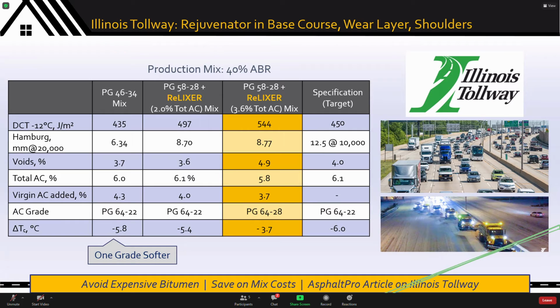to be able to make mixes. This was about maybe at least 20 hours of mix production, lay down of about 8 to 10 lane kilometers on base course, on wear layer course, and shoulders. They also employed 1 grade softer bitumen. In this case, the Rejuvenator, that one of the test cases was a Rejuvenator 1 grade softer.